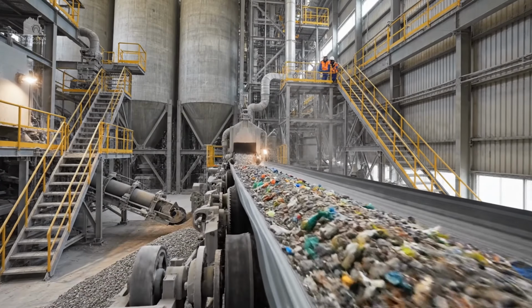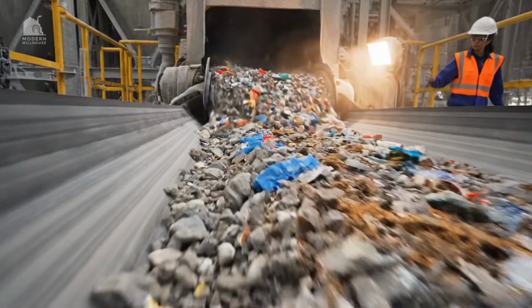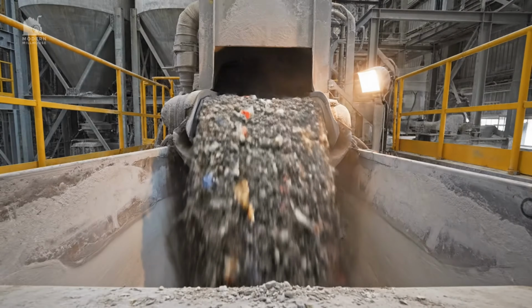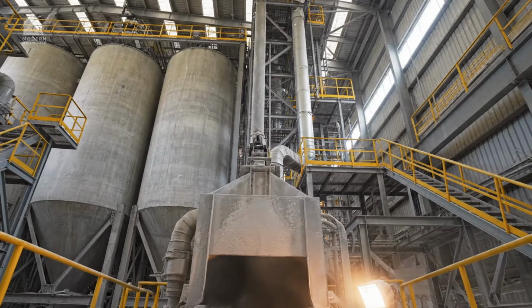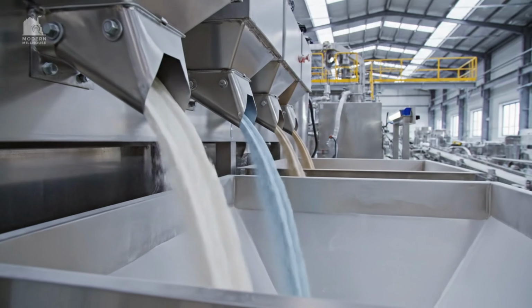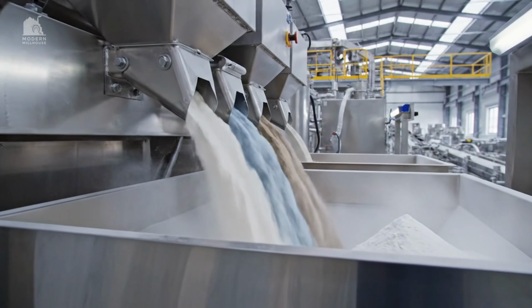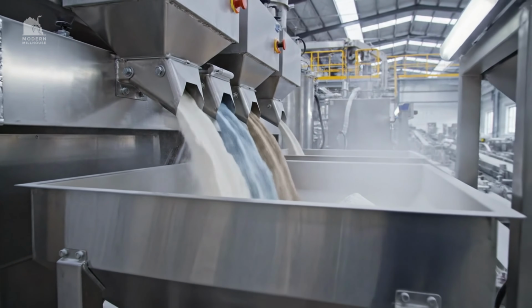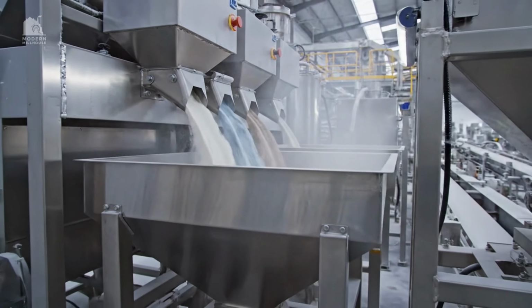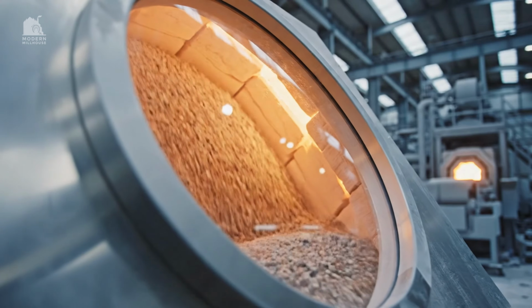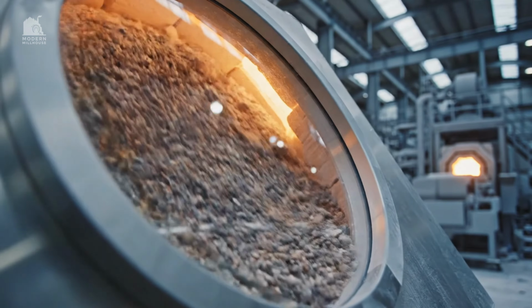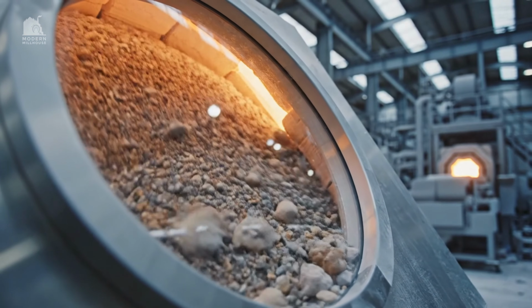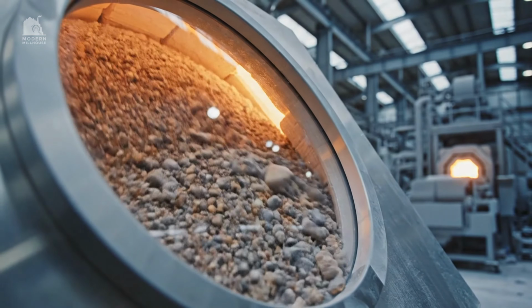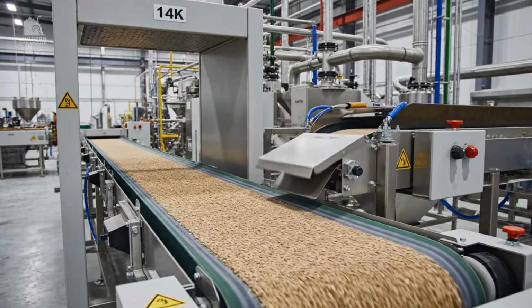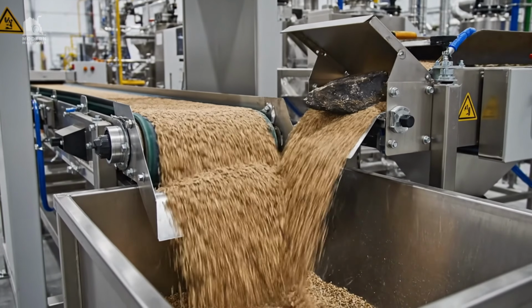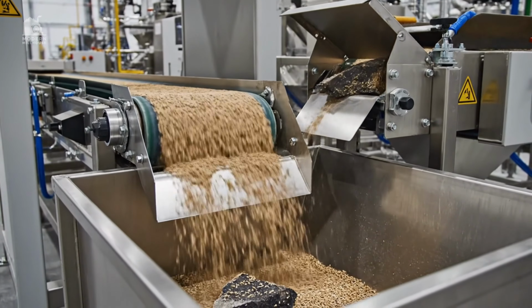Plants also remove tramp materials, bits of wood, plastic, or stones, because they burn out or expand and create voids. In blended dry systems, operators also control the feed rate, so materials do not pulse in waves. Pulsing creates alternating rich and lean zones of flux, which can show up later as size variation after firing. Some plants install metal detectors and stone traps to protect mills and prevent catastrophic tool damage.